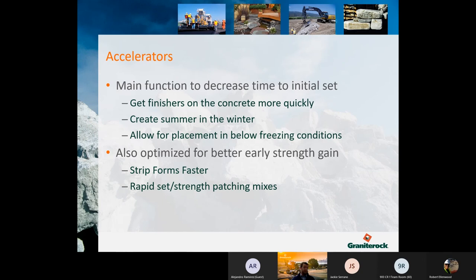Main function is to decrease initial set time. This gets finishers on the concrete more quickly. So if you're running a job, it lowers your time finishing it, which can be helpful. It creates summertime set times in the winter, allows for placement in below freezing. Concrete really doesn't set much below 40 degrees, so using an accelerator helps extend the range. We don't see that too much here just because our temperatures can be helpful. It can also be optimized for early strength gain, so if you want to strip your forms faster, or a rapid set, which can be used in patching applications.